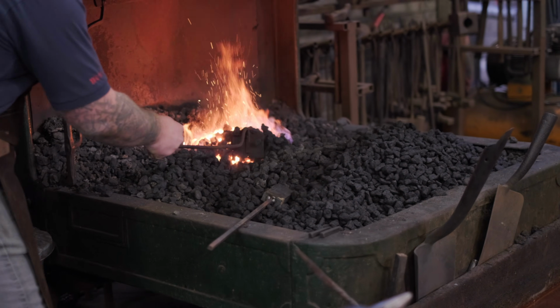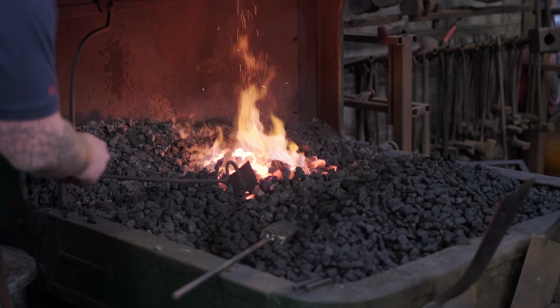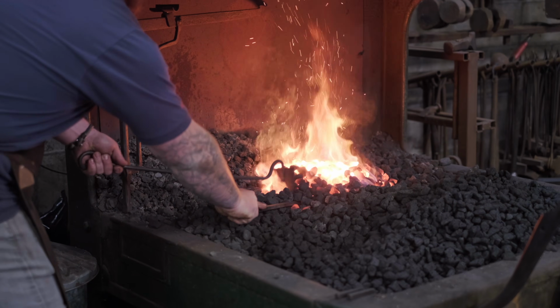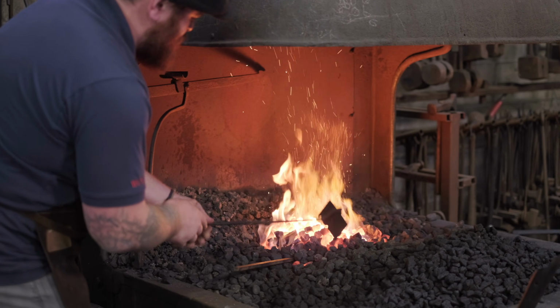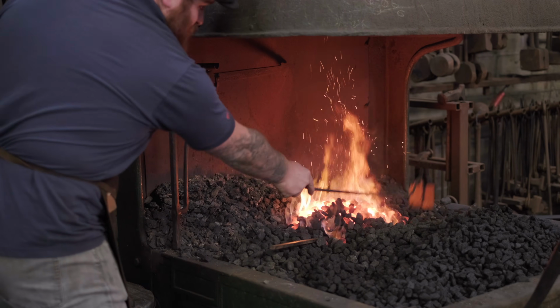Inside the middle of that ball of red hot coke, there's no oxygen. Because coke is just pure carbon, it's burning up all the air, it's generating heat. And in the middle of there, you've got a pretty much neutral or reducing atmosphere, unless you're blowing an extra lot of air in there to get it hot. So when you're forging your Damascus together, you don't want to be creating oxides on the surface, because that's going to make it not so easy for the stuff to stick together.